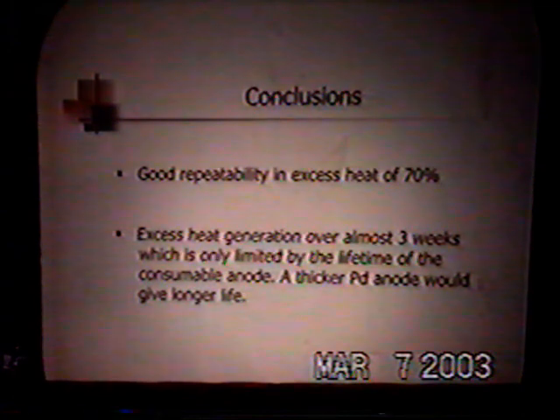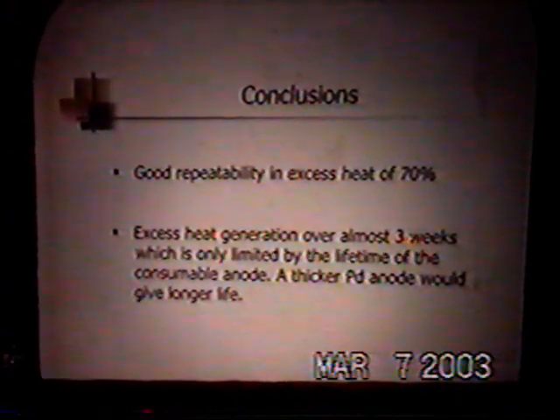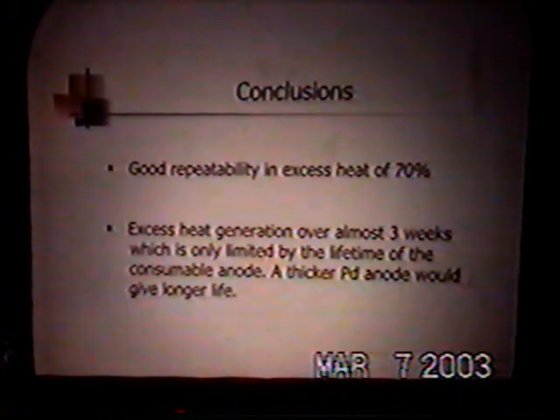So the conclusion is that we've done this now enough to argue that this particular process does give good repeatability, and the generation lasts over a number of weeks. Actually, it's only limited, we think, by the lifetime of the consumable anode, but we can put a new anode in, so it has a long lifetime. Thank you.